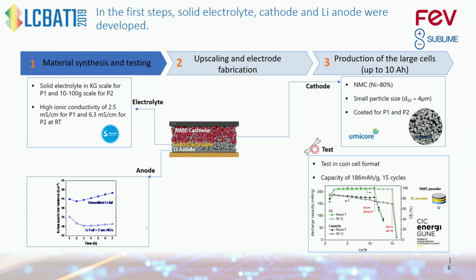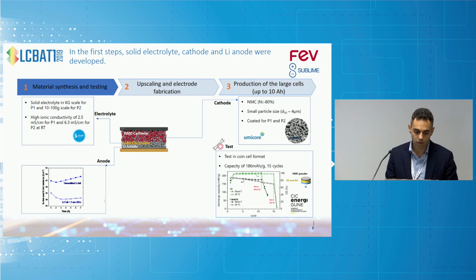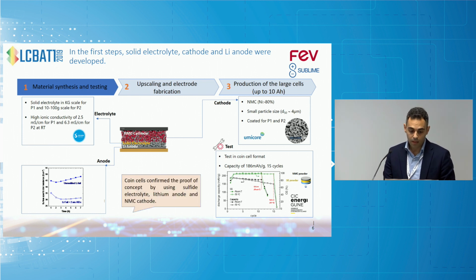The cell is working. I have to emphasize that the cell that you can see here is with the normal lithium anode, and this lithium anode was not coated. Therefore, the cell stopped working after several cycles. But this shows that the cathode is working, the solid electrolyte is working, and the lithium anode is working. But we have to upscale the lithium. We have to mainly focus on the development of the coating for the lithium anode.